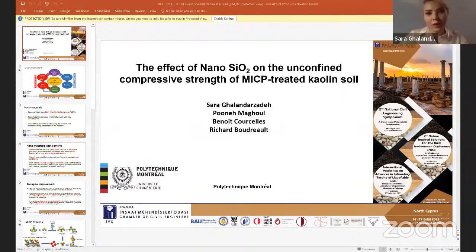To be more precise, nanoparticles have high specific surface area and may not chemically react with clay constituents. So their effect is limited to changing the texture and compressivity properties of the host soil. Nanomaterials such as nanosilica can act as an active pozzolan. This pozzolanic reaction can flourish when they are used along with lime and cement, but this use of lime and cement may create some detrimental environmental problems. So there is a new nature-friendly biological method named microbially induced calcite precipitation, which shall gradually replace the nature-harming traditional methods.